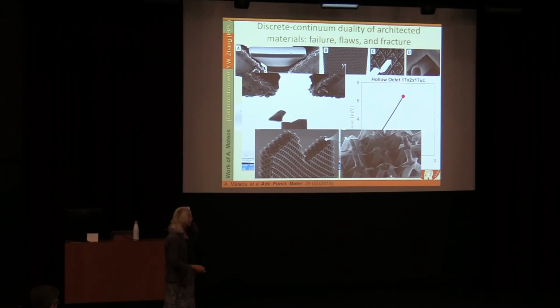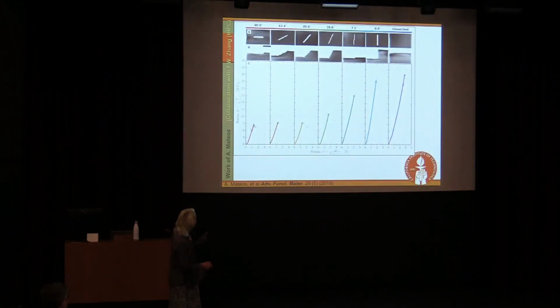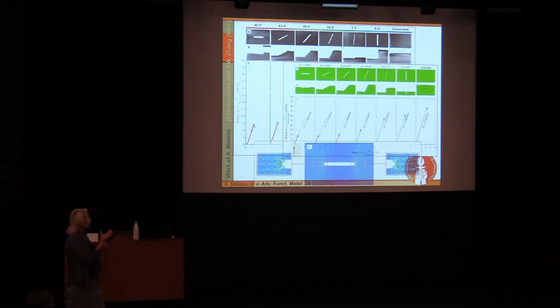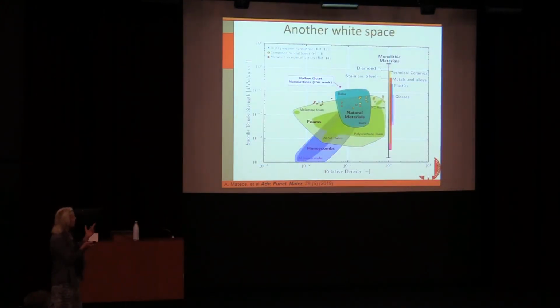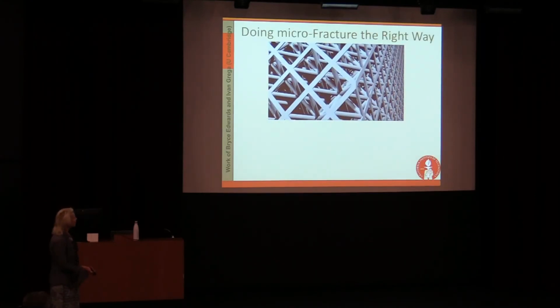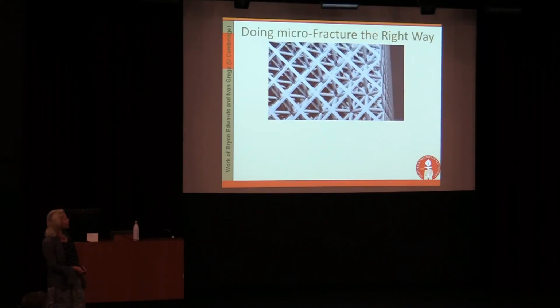We learned that they always fail orthogonally to the loading direction, no matter which way the defect is oriented. So that gives you a certain amount of comfort because you can put in a notch or a defect in any orientation that you want, and it always fractures orthogonally to the loading direction. And by doing this, we learned that we can actually hit another white space. So these materials don't ever cease to surprise us. Now, this is doing fracture the right way. That was not the best way to do fracture.